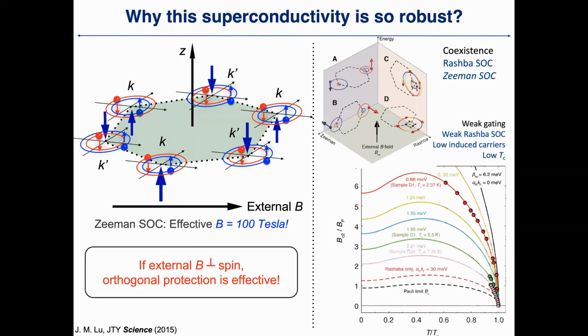So what happens there is a mechanism we call Ising superconductivity. So the Brillouin zone of the TMD, in particular molybdenum disulfide, has this kind of spin texture at K and K prime of the hexagonal Brillouin zone, and the spin is split at K and K prime points, and they are actually alternating between K and K prime.